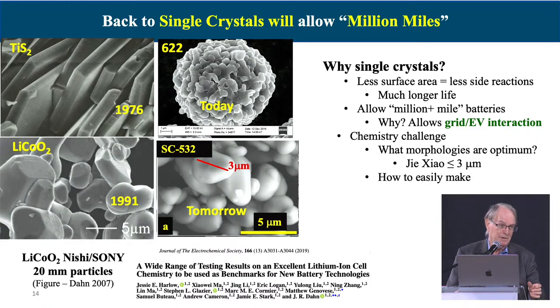of making these single crystals, and how might you make them, say, on tonnage quantities rather than a few grams at a time. So Jie has determined that if you keep it below about 3 microns, they won't crack, and I'll show you the importance of cracking in a few minutes.